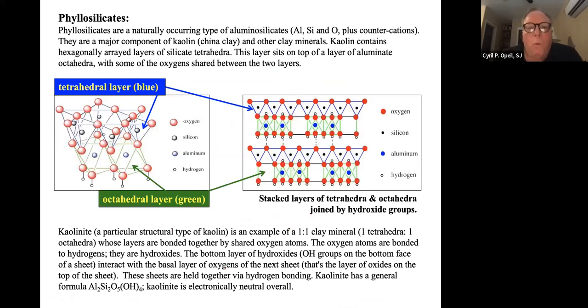Now, why is there negative thermal expansion? So I mentioned before that CM2s have olivine, pyroxene, but also they have phyllosilicates. And phyllosilicates basically are aluminosilicates, and they have a tetrahedral layer and an octahedral layer in the actual material. And so we have oxygens. This is three-dimensional, and this is just a side cut. So here's oxygen, silicon, aluminum, and hydrogen.